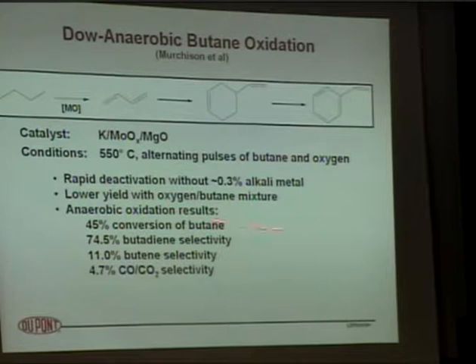They ran this process not in a real continuous mode, but in a fairly large scale reactor, pulsing in butane and pulsing in oxygen, so kind of doing it alternately between anaerobic and the regeneration mode. The data is shown here, and talking to Craig Murchison, who did a lot of this work, they did see a significant improvement over the straight dehydrogenation of butane to butadiene. So once again, great technical success, went through the pilot plant stage and failed because of economics.